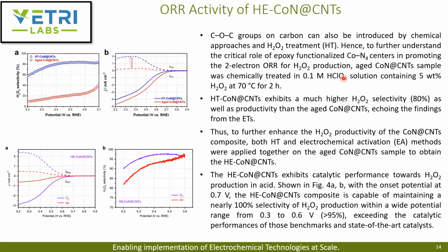As we saw earlier, they chemically treated it in a 0.1 molar perchloric acid solution containing 5 wt% peroxide. When they compared the aged one with the peroxide-treated one, the ring current increases, and so does the selectivity. The selectivity increased from 20% to about 80%. They wanted to further enhance the electrochemical production of peroxide and increase its selectivity, so they combined the electrochemical activation and the peroxide treatment and called it HE-CoN@CNTs.